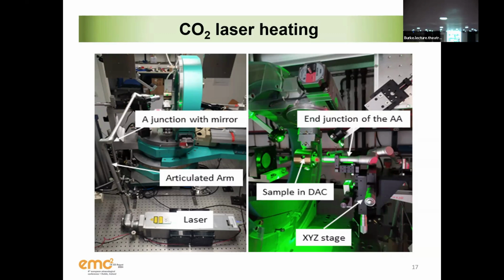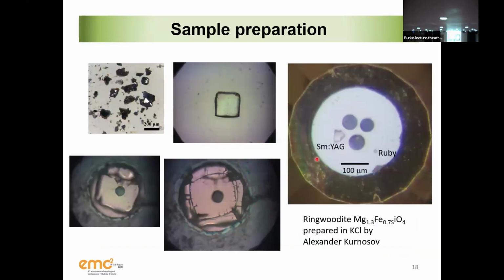So when you do this, you can have your single crystal, and with the same setup we can heat with a laser from one side, and we can measure Brillouin scattering at the same time. The problem is that the sample preparation becomes very complicated, because if you want to heat at high pressure, you need to use a lot of power. But with this arm, we cannot just use the 2-watt power of the laser. So we need to isolate our crystals between some isolation material, which is normally a salt.